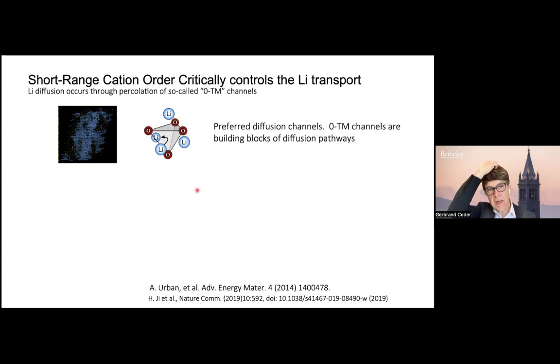So cation short-range order is actually the statistical preference for ions to surround themselves with themselves or another ion, a preference that's different from random. Okay. And if you remember, our percolation theory was built on fully random cations. And if you remember, what we want is these zero TM channels.